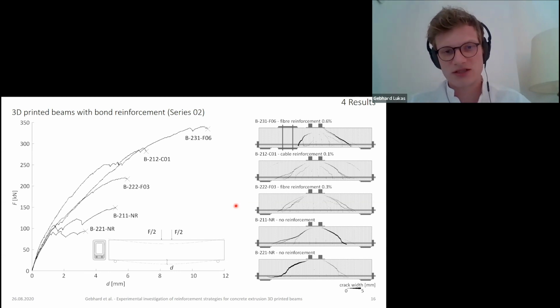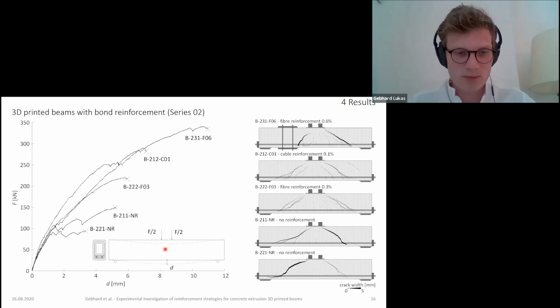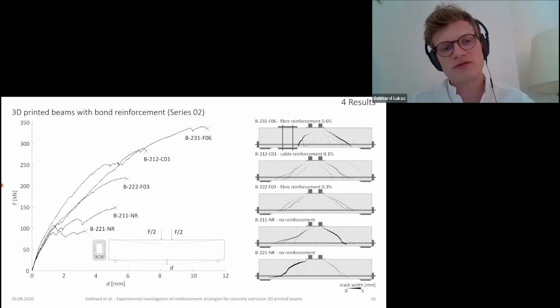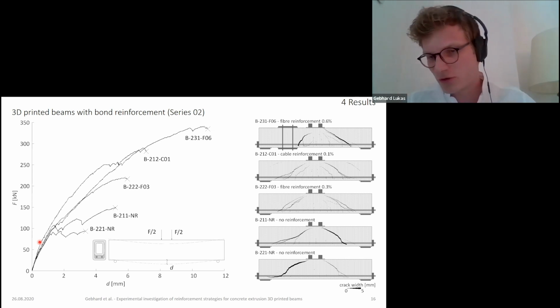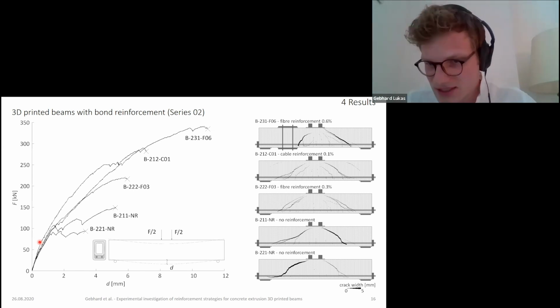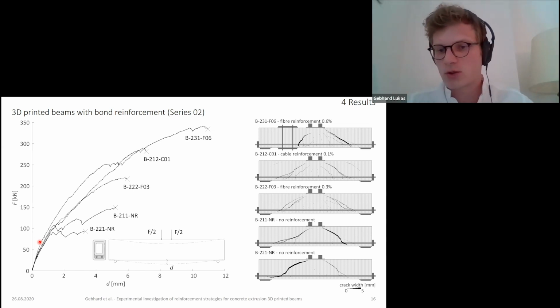On the other hand, for series 02, we can see again the load deformation curves on the left with the midspan deflection and the force applied, and on the right, the crack pattern where the line thickness indicates the crack width. If we go from bottom to top, we see the behavior of the two unreinforced beams down here, where at around 100 kilonewton they start to form diagonal shear cracks, and they only have these single shear cracks, which open quite largely, which you can see on the right for the two bottom figures.